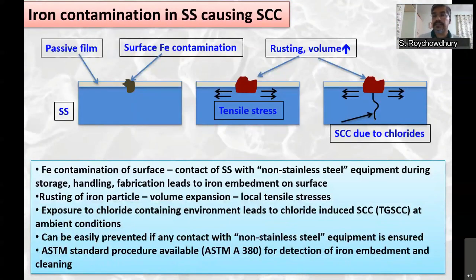So all these materials are good enough if they are handled properly. What I have shown here in this figure is certain things that can go wrong during the fabrication stage, during handling or during storage, which can compromise this high resistance to SCC. If this stainless steel comes in contact with non-stainless steel equipment, like say carbon steel, then there's every chance that a small chip of iron can break off from those carbon steel tools and embed into the stainless steel surface. Now this iron is prone to corrosion, it will corrode, rust, and there is a volume expansion which will lead to generation of local tensile stresses.